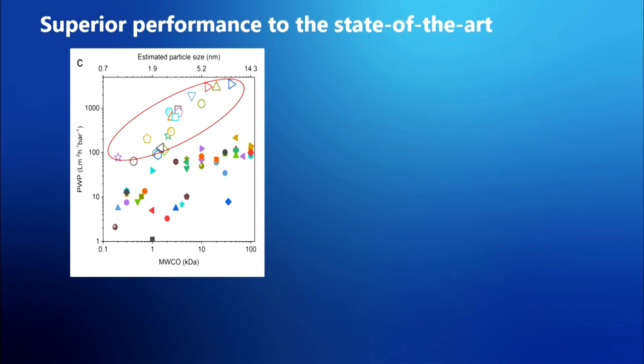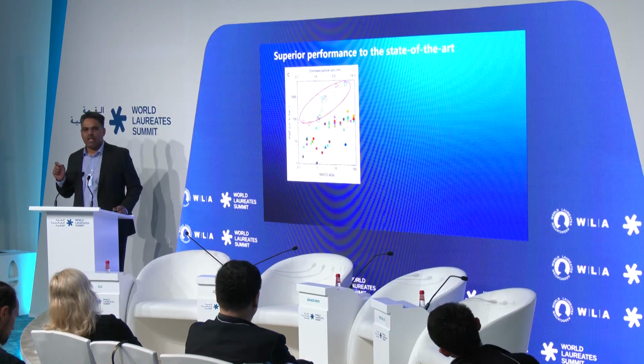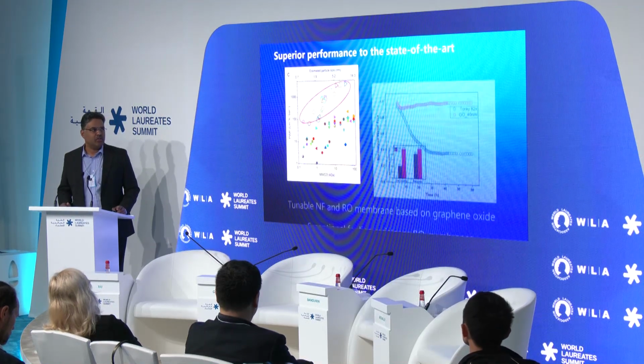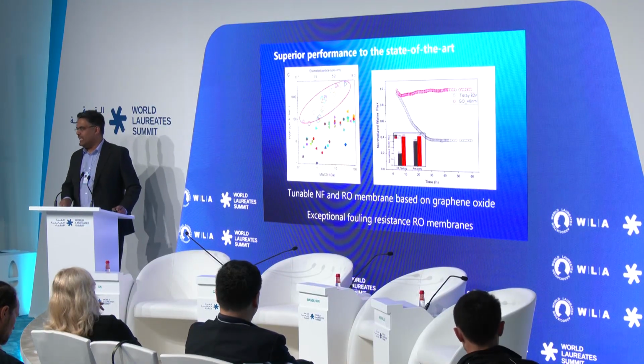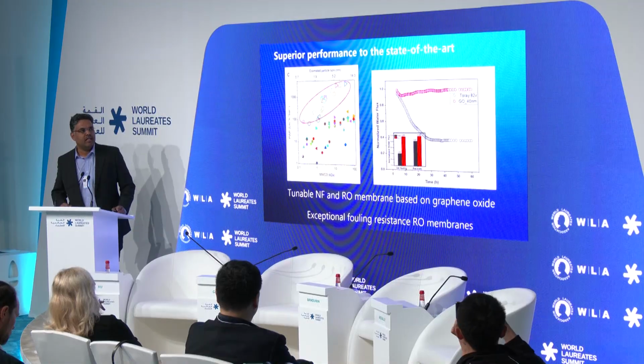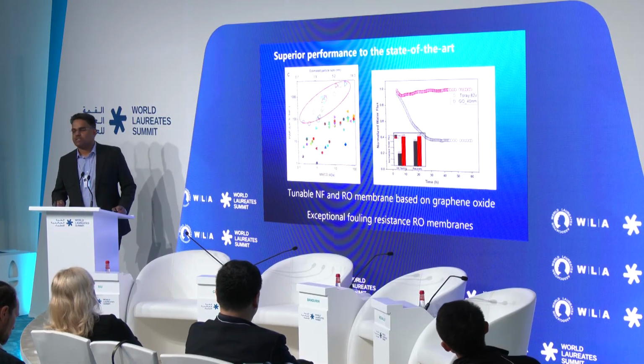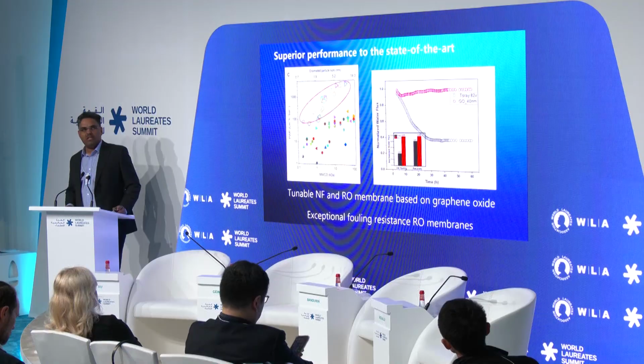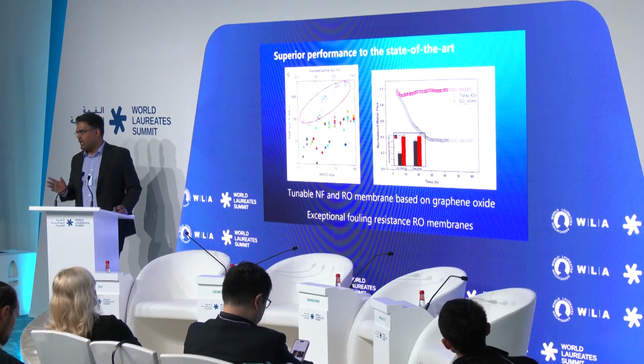Now, if you look at performance, you can see the open dots are from graphene-based membranes. The flux is orders of magnitude higher than the solid data points, which are from commercially available membranes. And with graphene, the beauty is that we can control the pore size from tens of nanometers down to even sub-nanometer by tweaking the formulation of the material or changing its functionality. Now, if you are specifically interested in seawater desalination, this is a comparison of data we created in our lab. The red data is from a graphene-based membrane for seawater desalination, and the black one is the state-of-the-art membrane available in the market, called a Toray membrane. That is the best membrane we can buy at the moment.